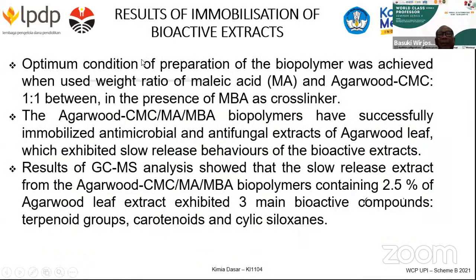So here is the result, the condition that we use. The hydrogel uses maleic acid and carboxymethyl cellulose, and we use a cross-linker here, and we introduce nanocrystal cellulose as well to improve the property of the hydrogel. And here, after slow release, there is still some bioactivity, and about 3 main bioactive compounds here from the Agarwood leaf, especially different groups, carotenoids and cyclic siloxanes.